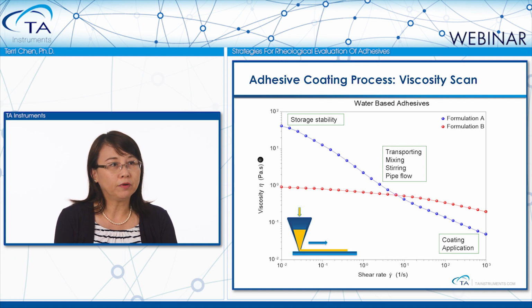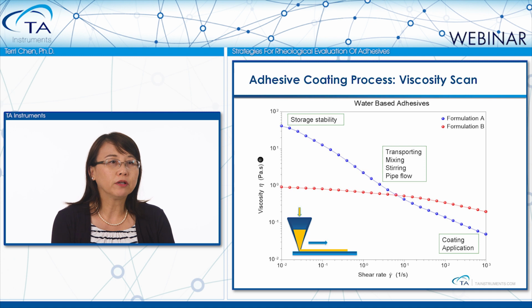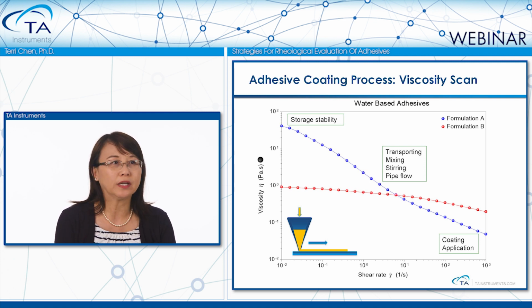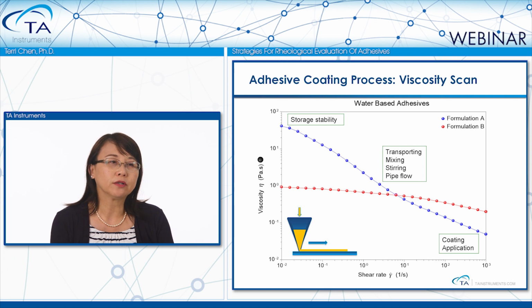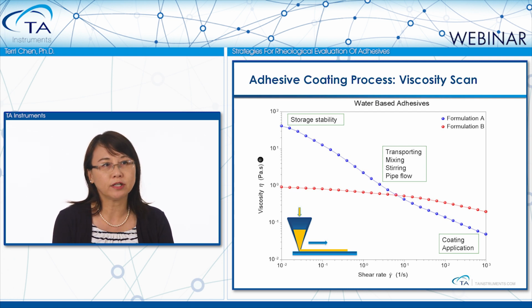Here is an example of 2 water-based adhesive formulations. Formulation A is more shear thinning, and formulation B is more Newtonian. So under low shear rate, formulation A shows much higher viscosity than B, which indicates that A potentially should have better storage stability against phase separation and sedimentation.